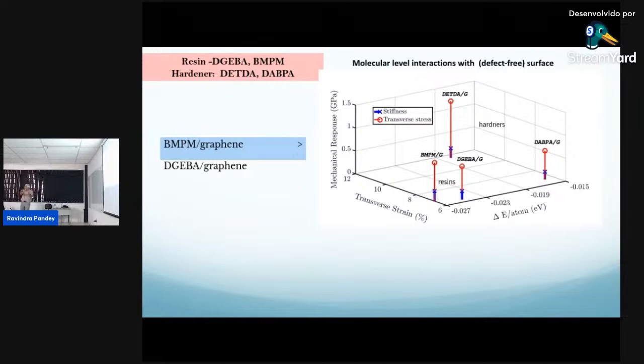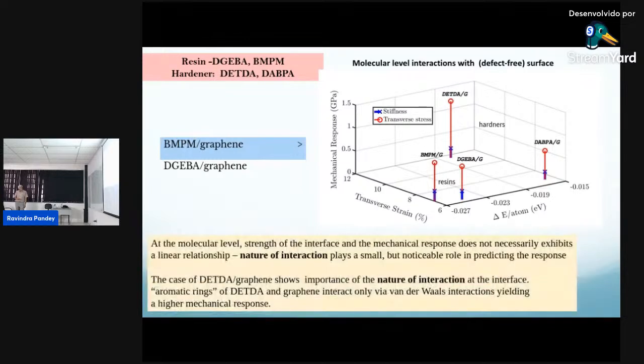So all these things can have different molecules, and what's coming out from this result is that the nature, you can see they are different. They are more or less the same molecules, but a single oxygen, single nitrogen, or two oxygens, they have a subtle difference in the interaction. That induces a different response. So nature of interaction does play a role, and then we talk about which one is better than the other molecules.